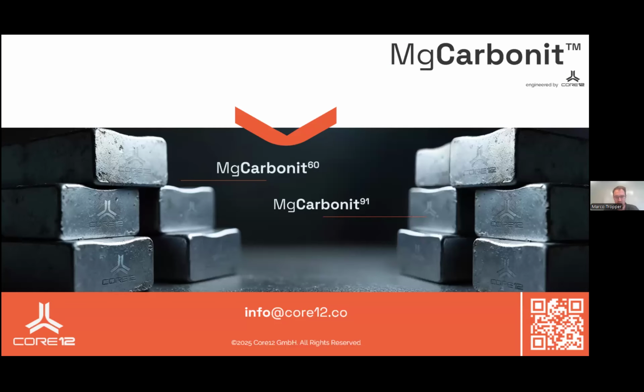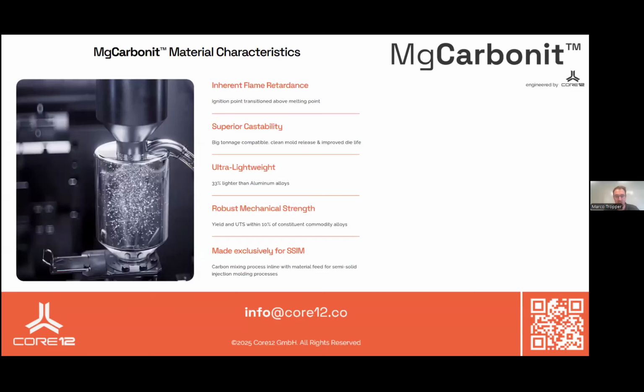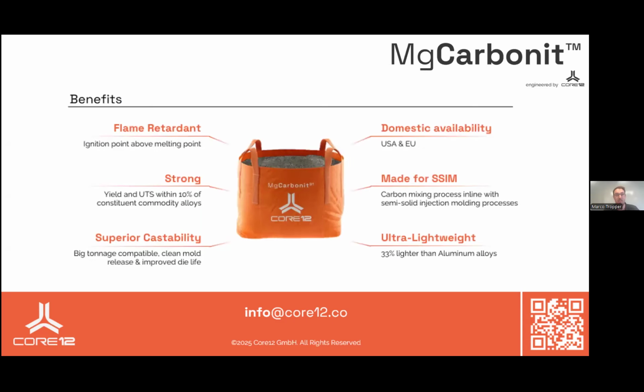And for MgCarbonit, there is no big tonnage anymore. But together with Core 12, we have developed MgCarbonit. So it's an inherently flame retarded alloy, and it's around 10% more strength than traditional AZ91 or AM60. Also, there is carbon powder inside that raises again the values of the material. And if you're interested in this flame retarding alloy for aviation business, e-bikes and so on, please feel free to go to